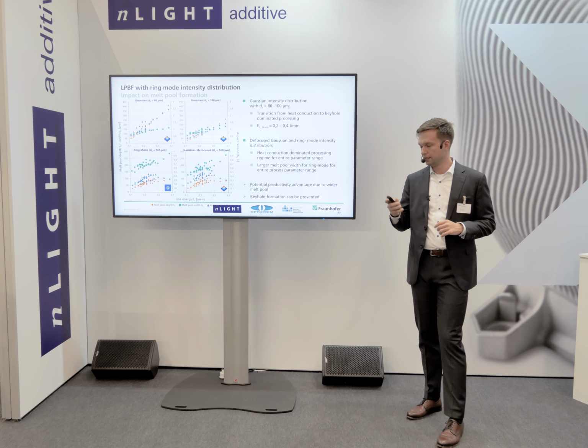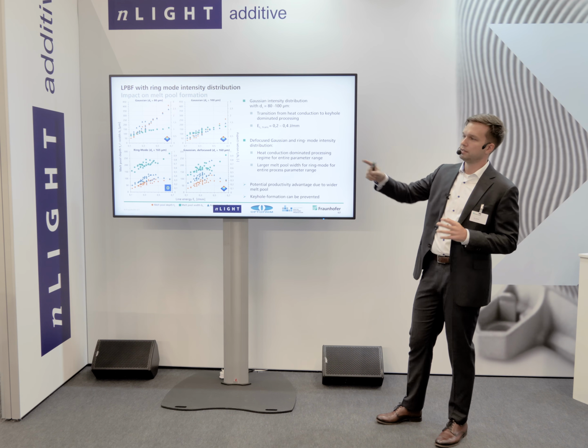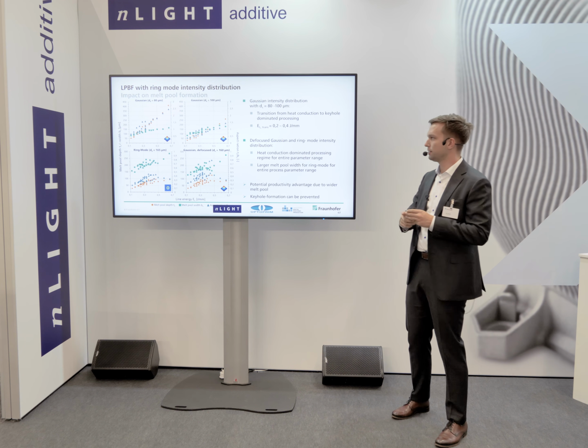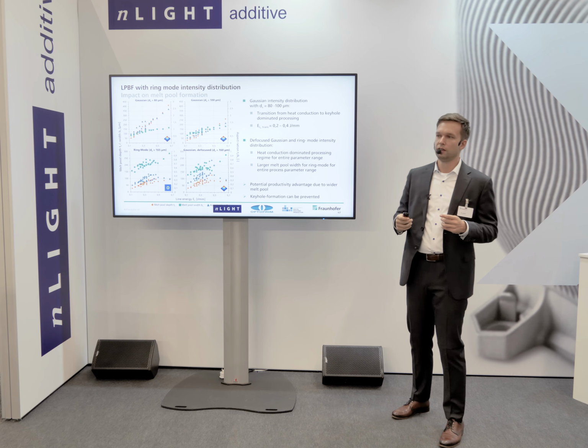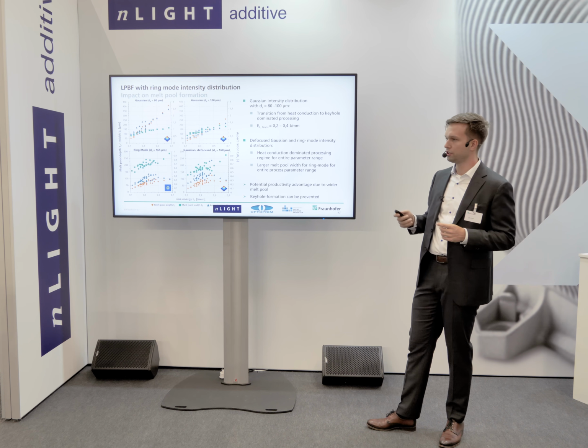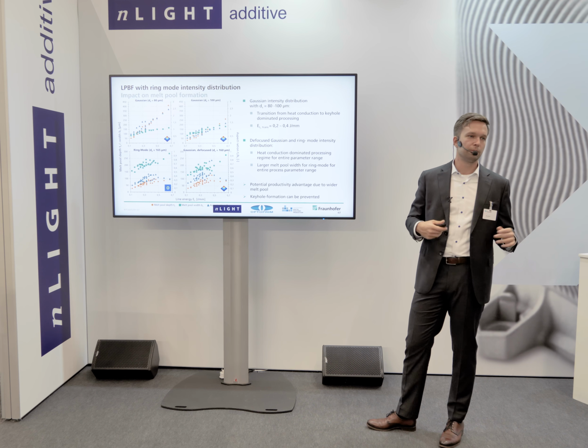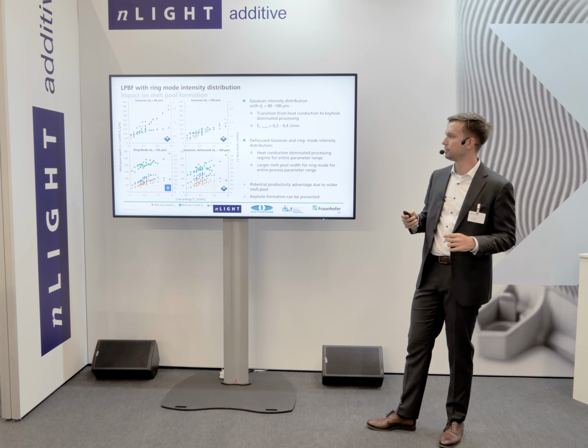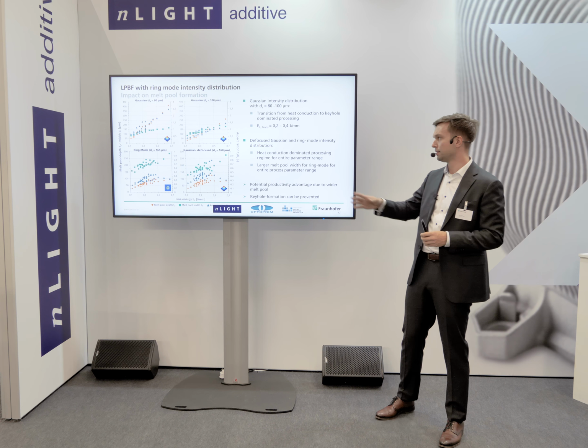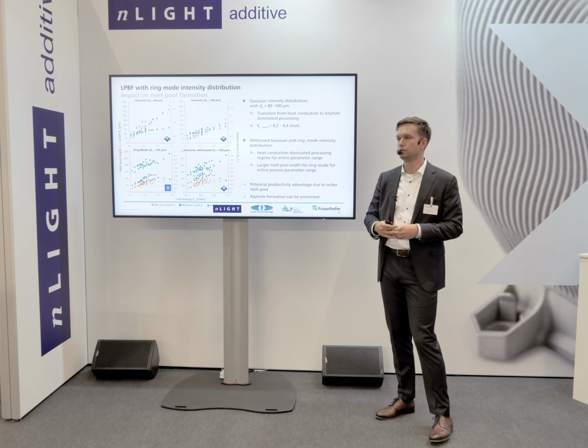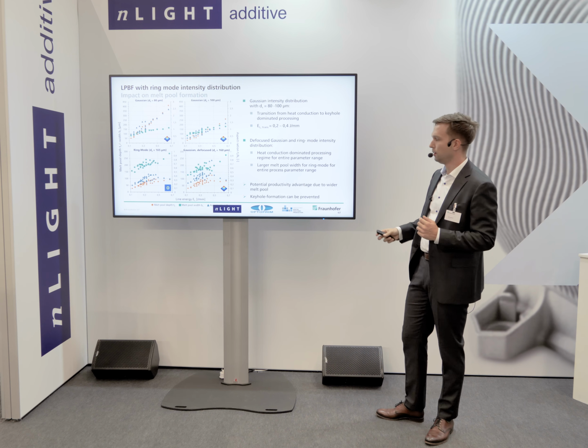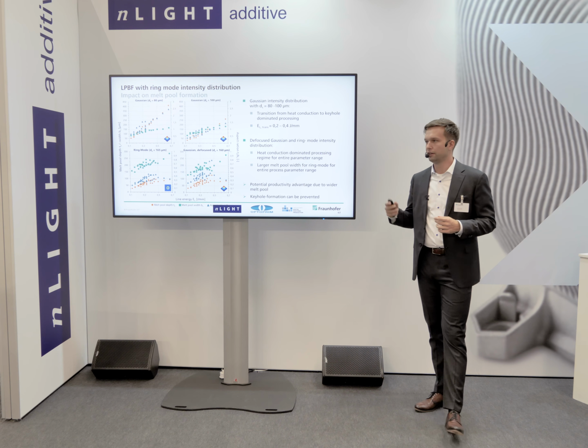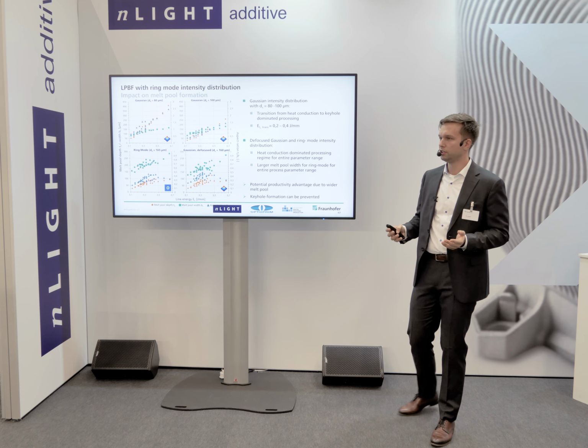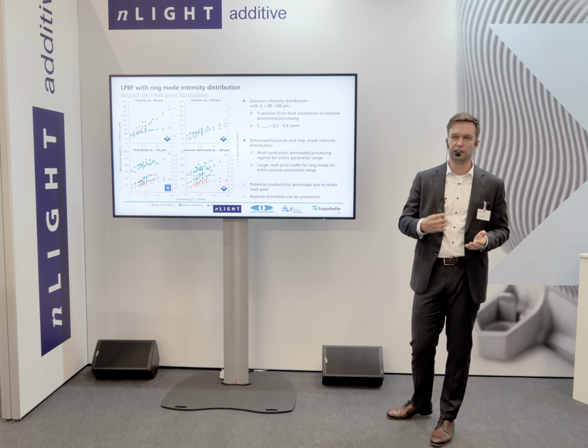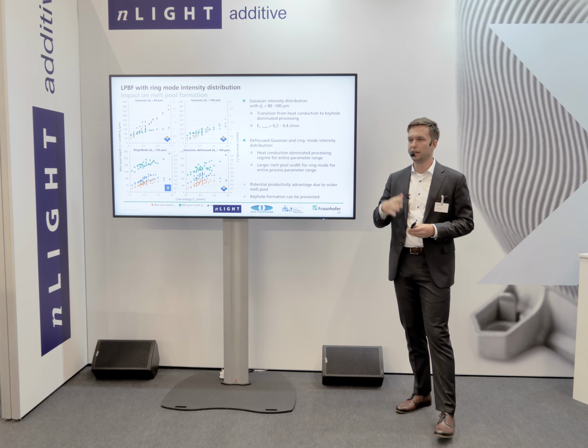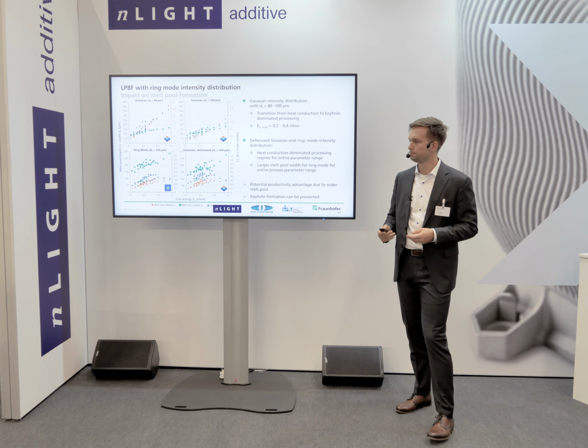And the interesting finding is that for the state-of-the-art Gaussian intensity distributions, you will at some point have a transition from a more heat conduction dominated processing regime to a keyhole dominated processing regime. And this transition occurs at approximately 0.2 to 0.4 joules per millimeter. Whereas for the defocused Gaussian and also for the ring mode, you don't have this transition. You always stick in this heat conduction dominated processing regime and do not have the risk of keyhole formation.